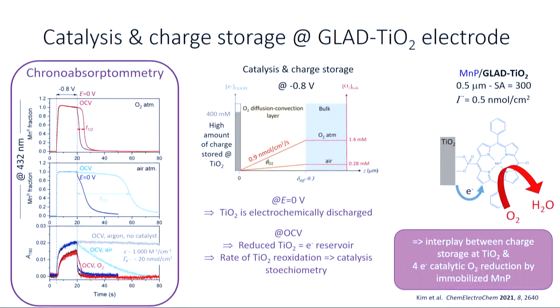And this correlates now with the fact that we have stored a significant amount of charge in the titanium dioxide electrode, and that the titanium dioxide is acting as an electron reservoir to pursue catalysis, even if there is no more reductive potential that is applied to the electrode, okay? And we need now time to discharge chemically the titanium dioxide electrode through the catalytic process in order to recover the manganese 3 state of the catalyst. So this is the first example of an interplay between charge storage at a semiconductive electrode and a catalytic process at an immobilized porphyrin.